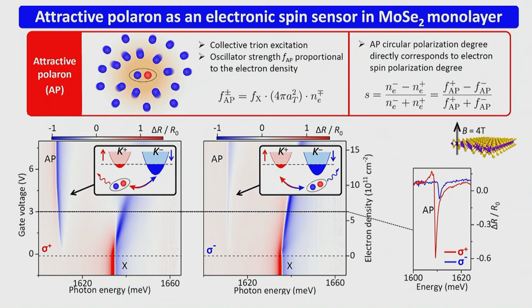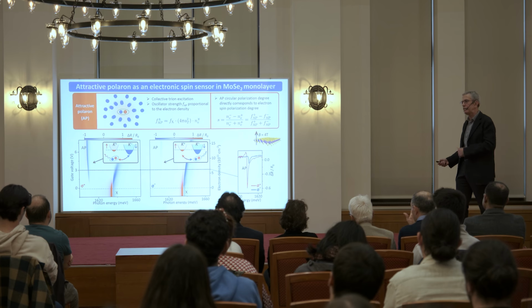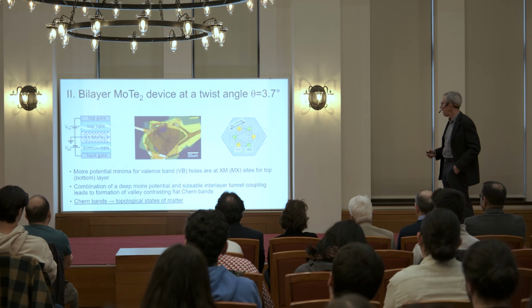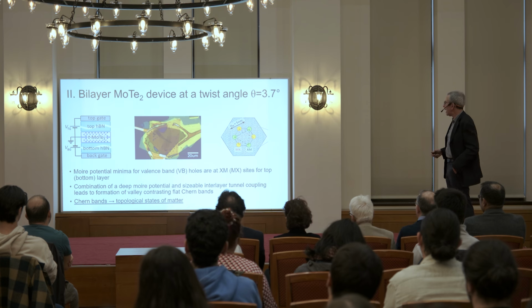So the strength of these transitions, or their ratio, directly tells us, and this we can show mathematically, the degree of spin polarization of the system. So if all the electrons are spin valley polarized, then this resonance is not there, and the relative ratios, as you can determine from these line cuts, tell you the degree of spin polarization in the system, and this is what we are going to use. Okay, so now the experiments.